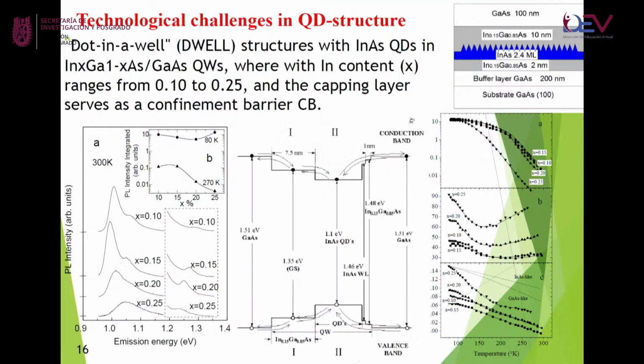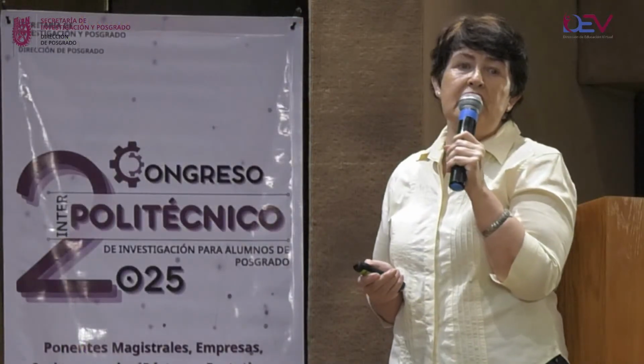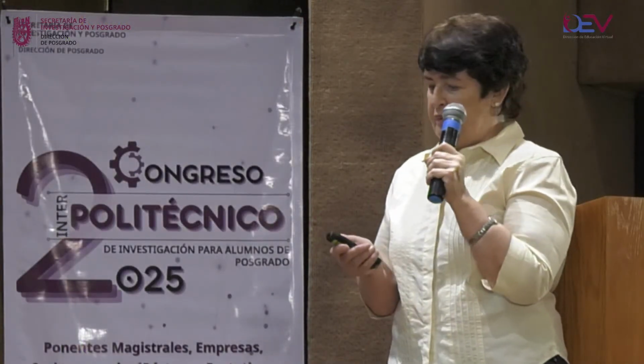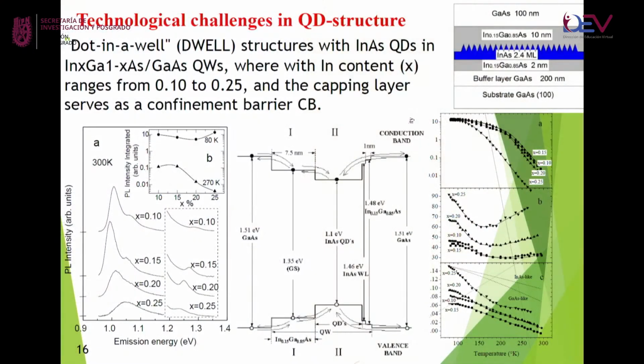Right now we talk a little about our work with this system. We start with a very simple system: gallium arsenide buffer layer, indium arsenide quantum dots. And we investigated 4 different compositions of the indium gallium arsenide capping layer, and the influence of this composition on the intensity of luminescence of the quantum dots.